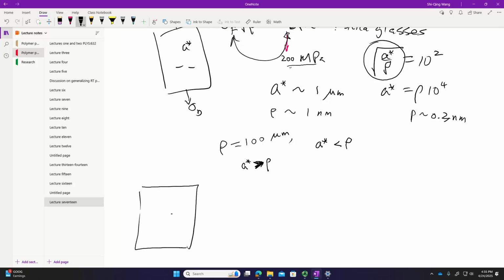If flaw weakens your material, your flaw size must be larger than this rho. Rho is all the mystery of fracture mechanics. And I haven't solved that myself. It basically is a material response to how failure can occur as they develop a crack.